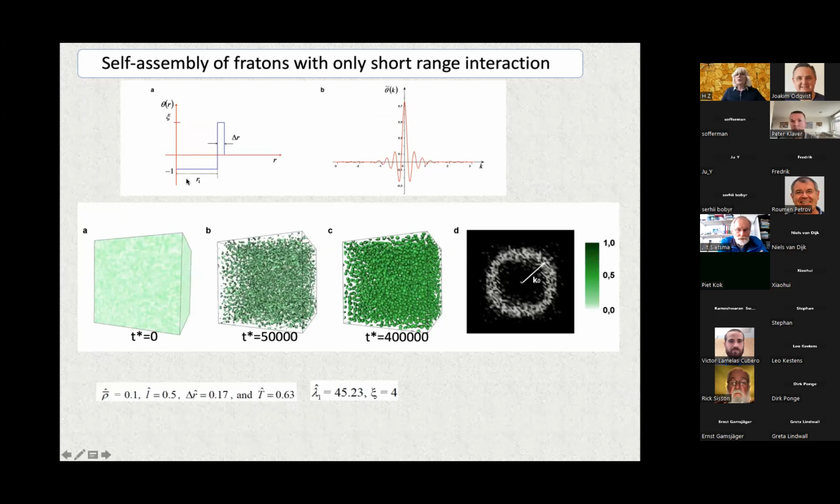If we introduce only short-range interaction, it means we fix only the size of the atom without a given symmetry, and we give some concentration of our phase field. We will obtain the creation of some number of atoms in a disordered state, and we can call this an amorphous state or gas state. It depends on the density of these atoms.